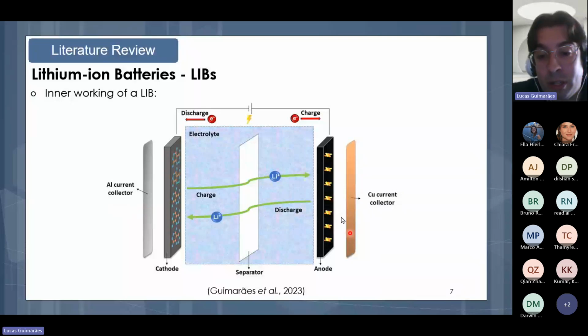And the same thing for the negative electrode, the anode: we have the anode active material glued onto the metallic copper current collector. And between them, we have this polymeric separator. It's important to have the separator because it avoids a short circuit inside the battery, since it keeps the electrodes from being in contact with one another.